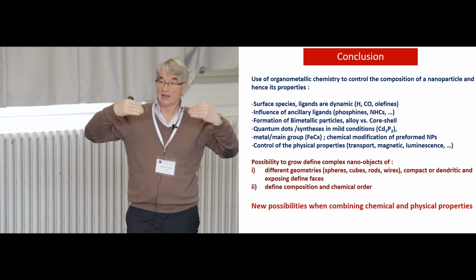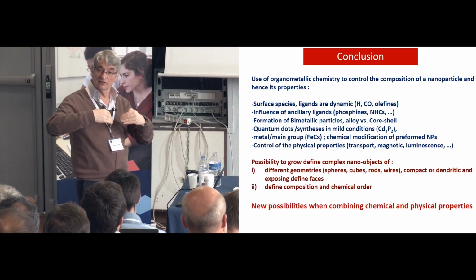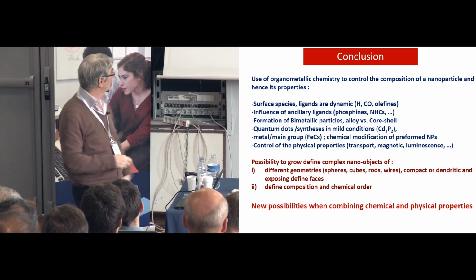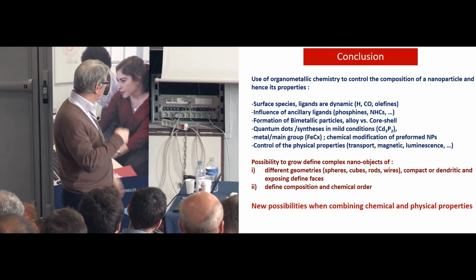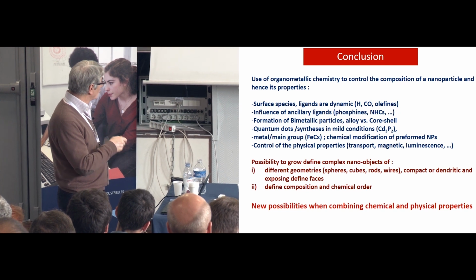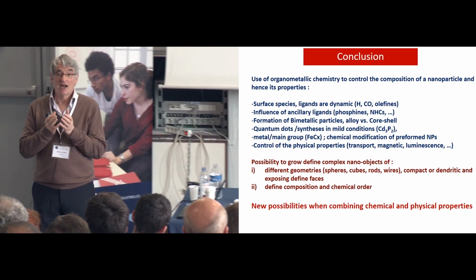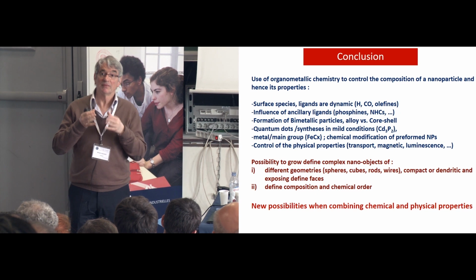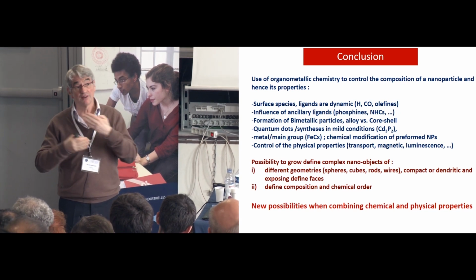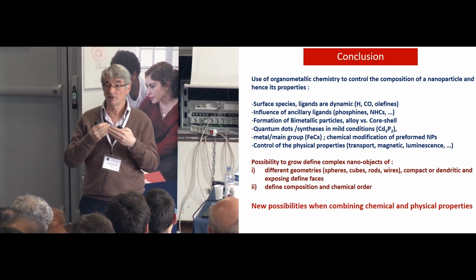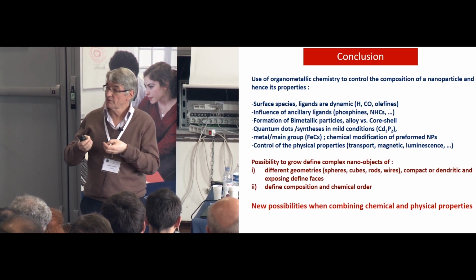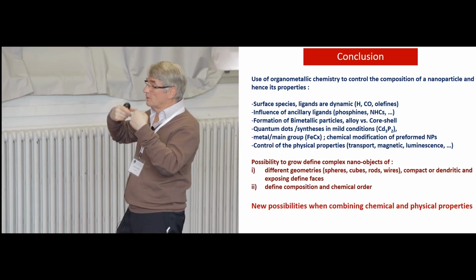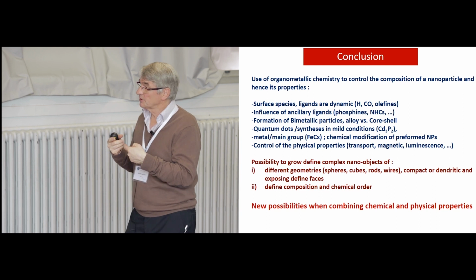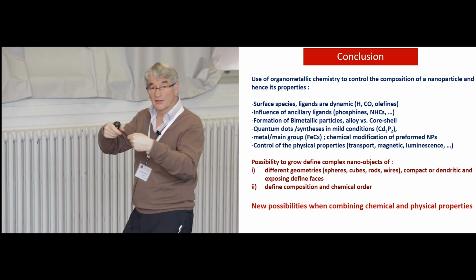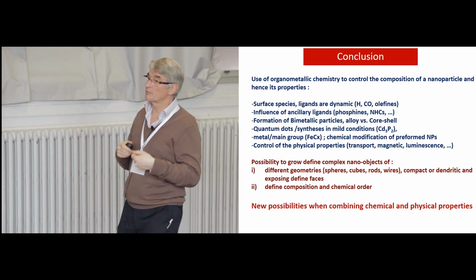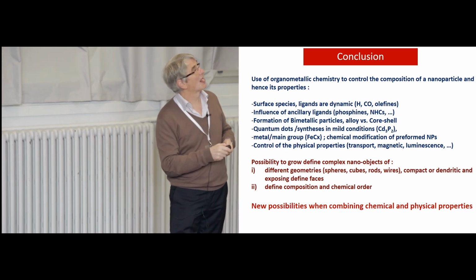The ligands are really ligands, not only surfactants. They bind strongly to the surface. You can make bimetallic particles. You can make compounds. I would say that so far, except for cadmium phosphide, we have not proven that organometallic chemistry is very important for quantum dots, but using the techniques of organometallic chemistry, we can understand what's going on during chemical processes with quantum dots.